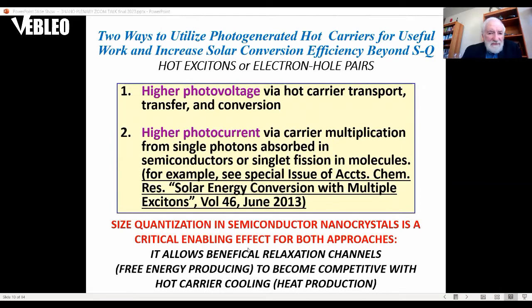So I'm going to be talking about utilizing the hot carriers for useful work to beat the cooling, and either extract the carriers or multiply the single electron-hole pair produced by a single photon into multiple electron-hole pairs by absorption of a single photon. So you can use the hot carriers two ways. You can extract them before they cool. You create these high-energy electrons. They're hot, they have excess energy, and if you can extract them out of the device that absorbs the sunlight into the external contacts and use them to produce electricity, you can do that.